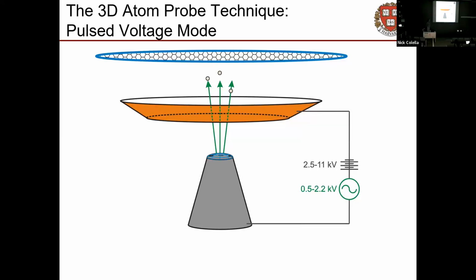Way before you get to that kind of field on something you can hold in your hand, your power supply will have caught on fire, all the wires will have melted, and you'll have ozone everywhere, and it's going to be awful. But you can do it with a very small object, especially a pointy object, because as we remember from E&M, if you have a pointy thing and you put voltage on it, you get field lines clustered at the pointy end, and you get very large field magnitudes for comparatively small voltages. In this case, a few thousand volts is enough.